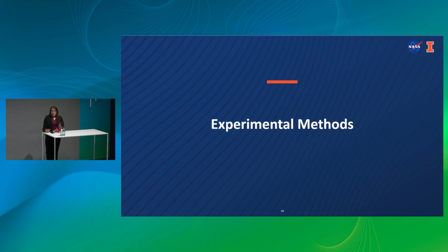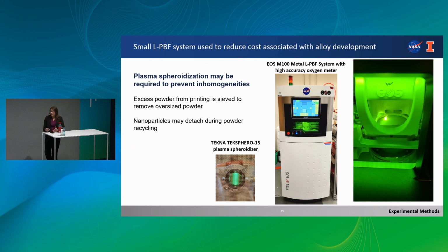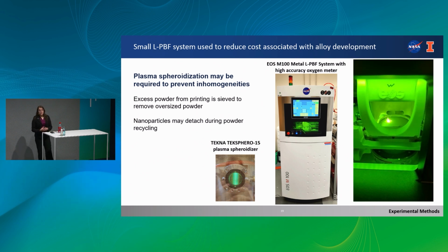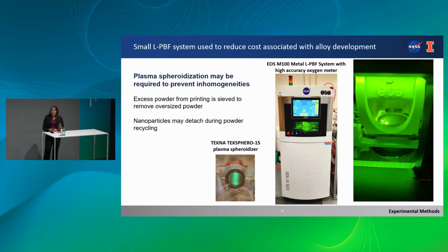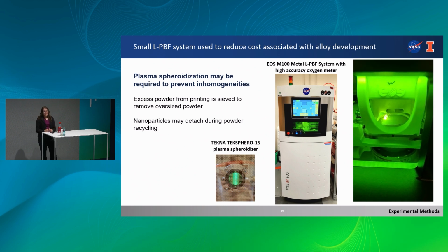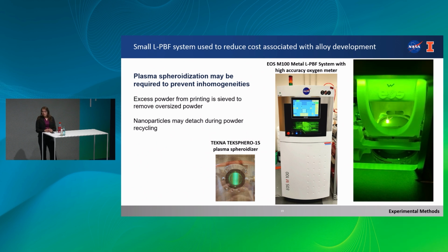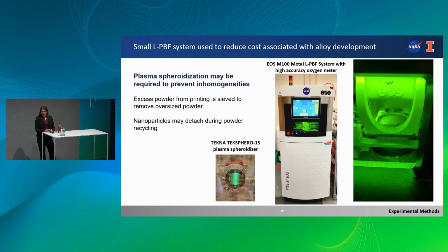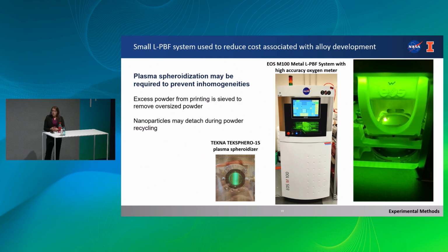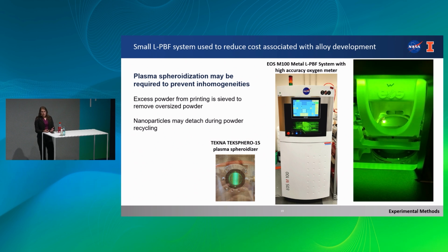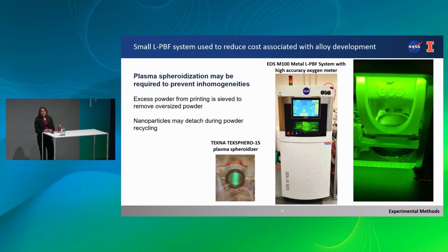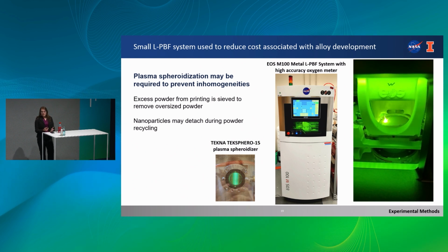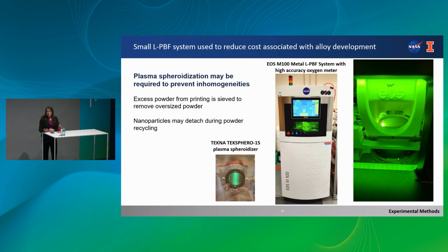So I'll talk a little bit about the experimental methods that we used. We used an EOS M100, because it has a small build volume. It helps reduce the cost associated with fabrication, and it also helps us rapidly manufacture these materials. Essentially, it's pretty quick to clean out. And of course, when we add these nanoparticles, the excess powder will be sieved, and so these nanoparticles may detach during powder recycling. So we've also got a Tekna Teksphero-15 plasma spheroidizer in case we see this nanoparticle detachment as we move forward with our studies.